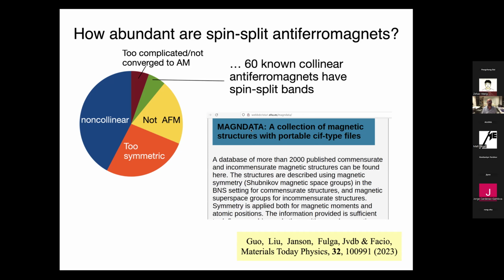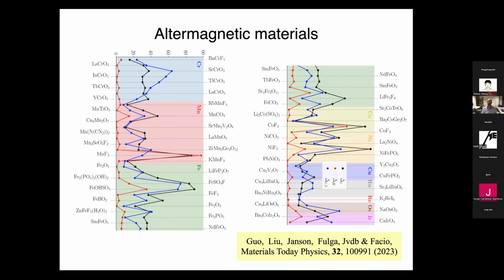What we did is look at a database of 2,000 measured magnetic structures and determine how many altermagnets we have. It turns out there are about 60. Nowadays, we know there are many more, but in the MagData database, there are 60 of them. And here they are. Some of them contain chromium, manganese, iron. There are cobalt ones, nickel ones, even cuprates that are altermagnetic.